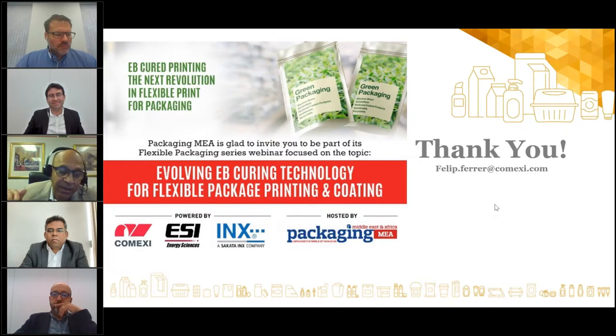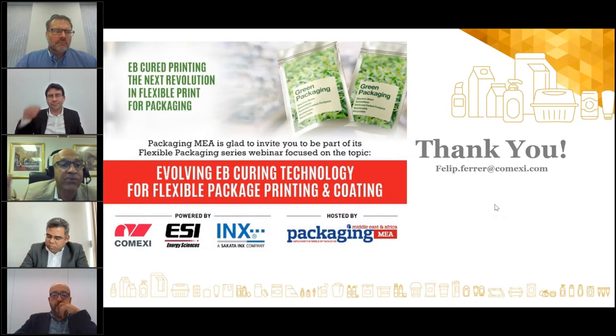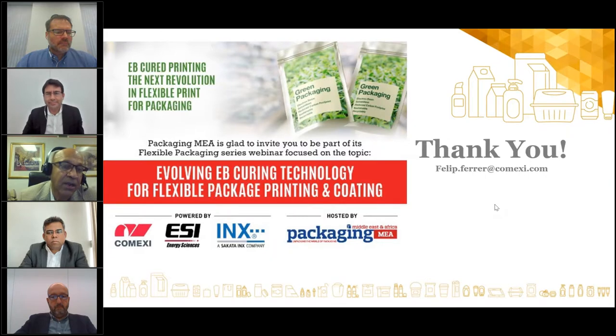And that EB lacquer is designed not only to meet all the migration requirements, like what Mike mentioned, but it is also designed to release from the cold seal adhesive. So you don't even need to put a silicone coating layer on top of the OPP film, which you were doing before. The EB coating itself is designed to release from the cold seal adhesive, because this is for a candy like a chocolate M&M or a Skittles application. So there's a lot of value to that.